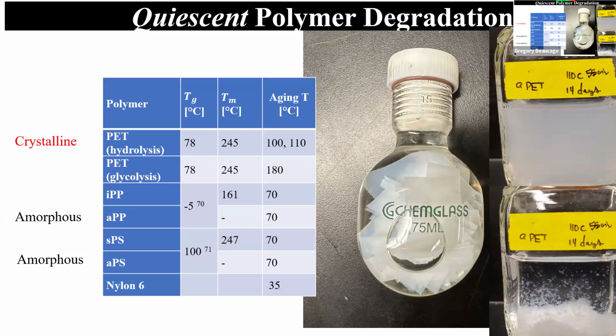So here is now an experiment at 110 degrees centigrade. That's why the thing is sealed on top, because water boils at 100 degrees. You can take it up to 110. It's still water. It's quiescent, but it's now starting to break bonds. So the idea is it goes into the amorphous phase and starts breaking bonds there. All right. After 14 days, we remove the plastic sheets out. This is what you're left with. So it's starting to fragment. You shake it up, it goes back into solution. But those are the micro and nanoplastic that I want to look at. So the melting point of the PET is 250 or something. Glass transition, like 70. So you're above the glass transition. I'm above the glass transition. So it wouldn't just kind of make a clump. What you see is what you got. Okay.